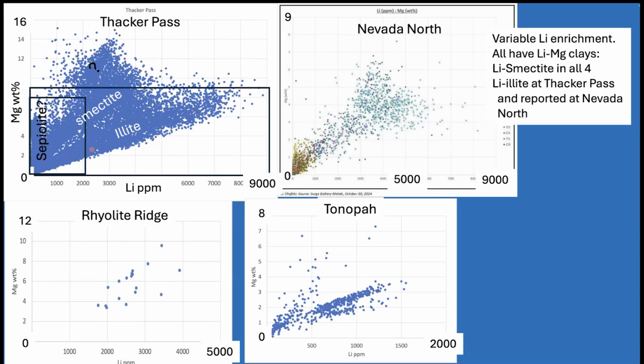Thacker Pass is our best example, and you can see there's a high lithium, low magnesium trend. As you remember, the illite has higher lithium, lower magnesium than the smectite. So this is the illite trend here. This trend here matches smectite, has a maximum value around 4,000 ppm. That's what we saw in our X-ray diffraction data previously.